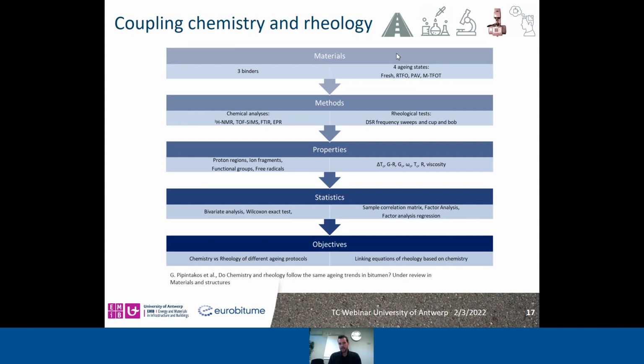They were used in 4 different aging states: standardized ones, RTFO and PAV, and also the original unaged binder. And also from the first study, the time interval at 8 days was used for all the binders with this modified thin film oven testing, since it was considered as the completion of the fast rate phase and the initiation of the slow rate phase. Then different methods were used, spectroscopic techniques that showed great potential, but also proton nuclear magnetic resonance, which can give us information about the proton regions.